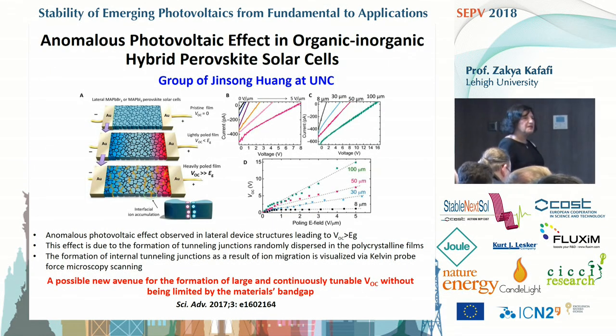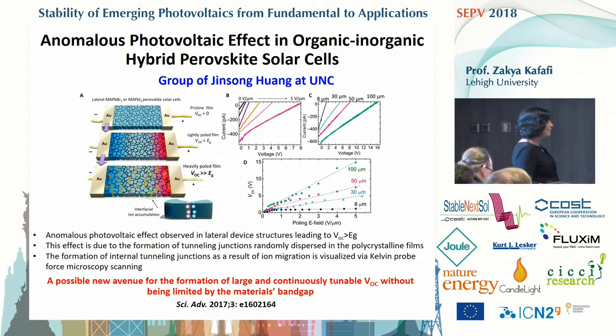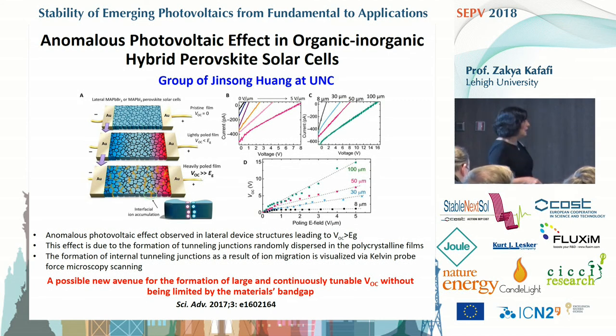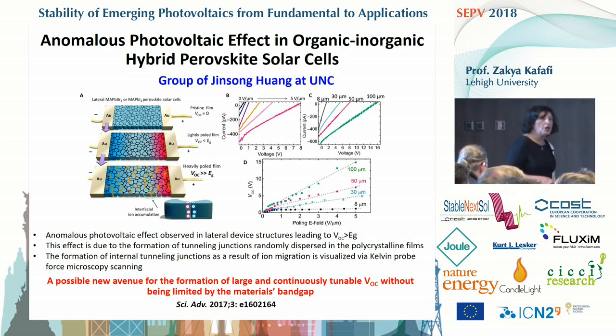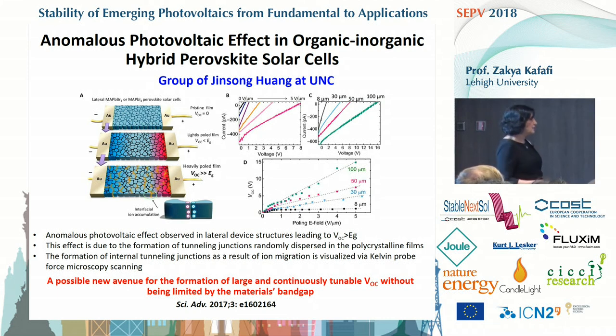He also demonstrated something very interesting, and if possible, it will open a new avenue for the formation of large and continuously tunable open circuit voltage without being limited by the material's band gap. He shows an anomalous photovoltaic effect in lateral device structure leading to open circuit voltages that are larger than the band gap. And he attributed this effect to the formation of tunneling junctions randomly dispersed in the polycrystalline film. The formation of these tunneling junctions as a result of ion migration, he was able to visualize using the technique of Kelvin probe force microscopy scanning.